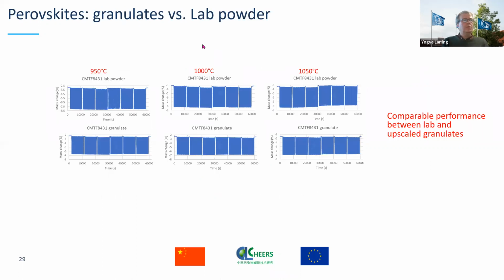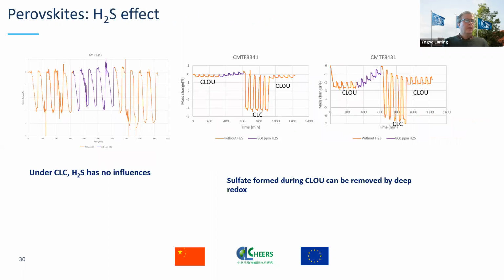And we checked also granulates versus lab powder, because we make powder in the lab, which is called sieved and crushed or such things. But the granulates made by spray granulation, we saw that we get rather equal performance on the material, which is comparable, which is very nice. This also is small scale or kilo batches.